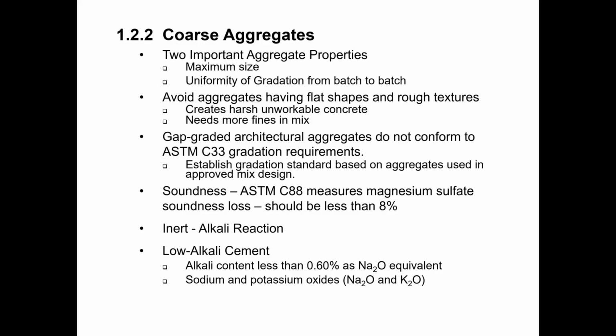But one thing to keep in mind is that if the project specification explicitly requires ASTM C33 gradation conformance, then if we're having to use an aggregate that does not meet C33 gradation requirements, we need to let the specifier know that. Generally, that's going to be either the architect or the engineer for the project. Generally, it's not going to be too big of a concern to them if you assure them that even though you're having to use a gap-graded aggregate, you'll still be able to get the desired strength and aesthetic performance out of the mix. But since you are not meeting a specified requirement, you need to notify the specifier that that requirement is not being met and get their approval to proceed.